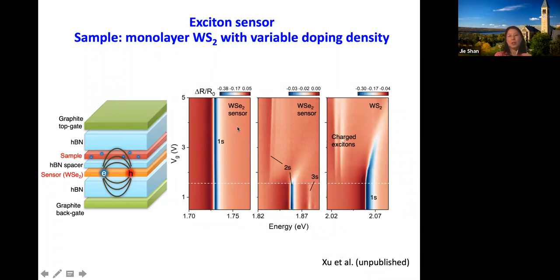Let's take a look at the sensor layer response. The 1s exciton doesn't change at all when we put doping into the WS2 layer. As I mentioned, the 1s exciton is tightly bound and small, so it does not feel what's going on in the sample layer, which is nanometers away from it. But the 2s exciton changes dramatically. It follows what's going on in WS2. You have this shift to lower energy, and then you can also see a 3s and higher. With doping in the sample layer, this disappears also.